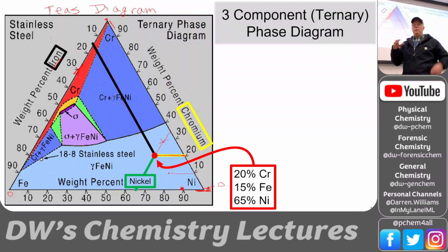And so a lot of them, they'll make the steel and then they'll pickle it. They'll put it in acid, and the iron is more soluble in the acid than the chromium or the nickel. So that's going to be a surface phenomenon. On the surface, the iron is going to get dissolved out in the acid, and it's going to leave behind a chromium nickel coating that's depleted in iron. And so that's a way to make the surface much, much less reactive by sucking the iron out of the surface. That would be an acid treatment to prevent rust.